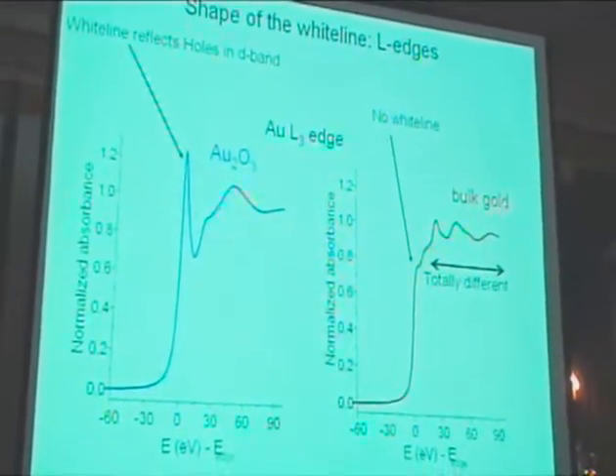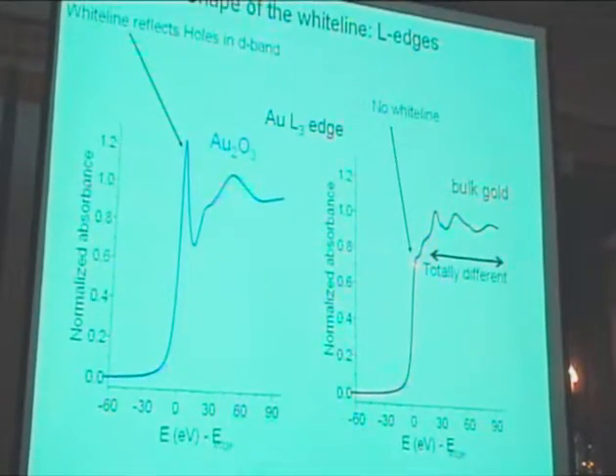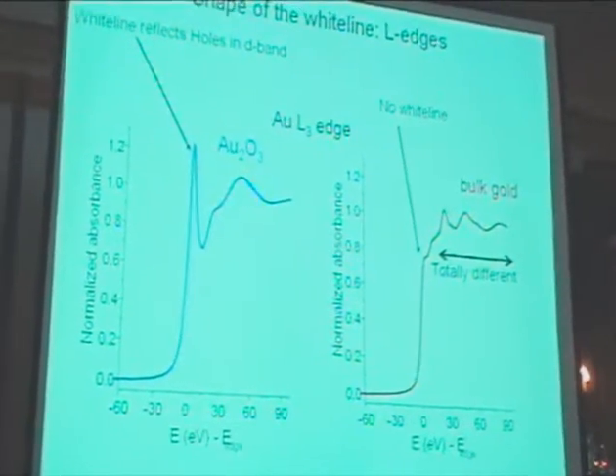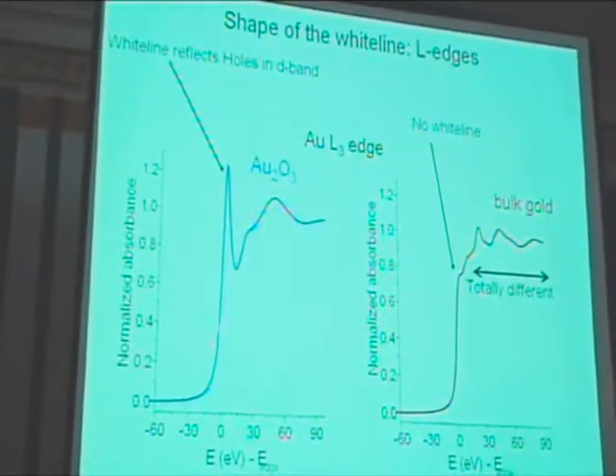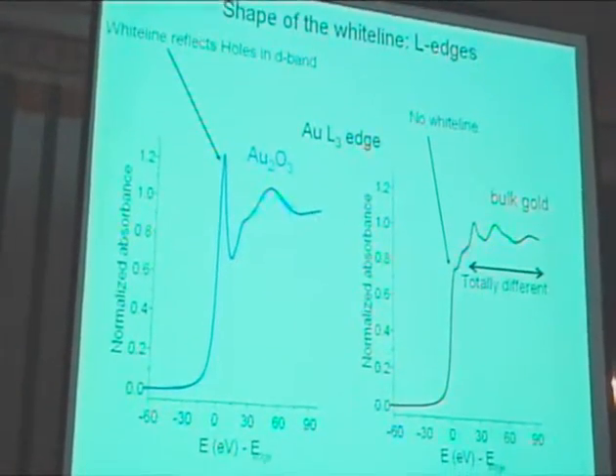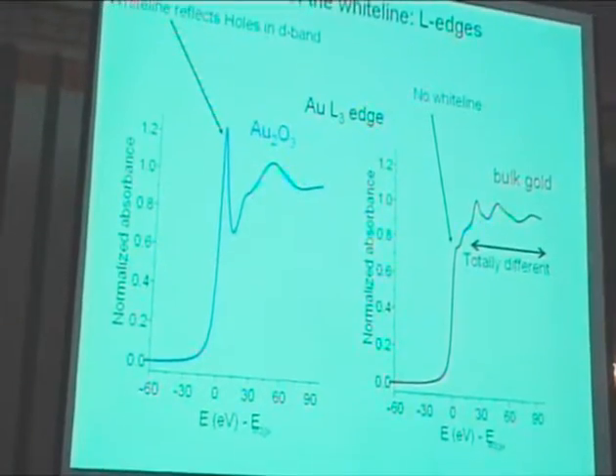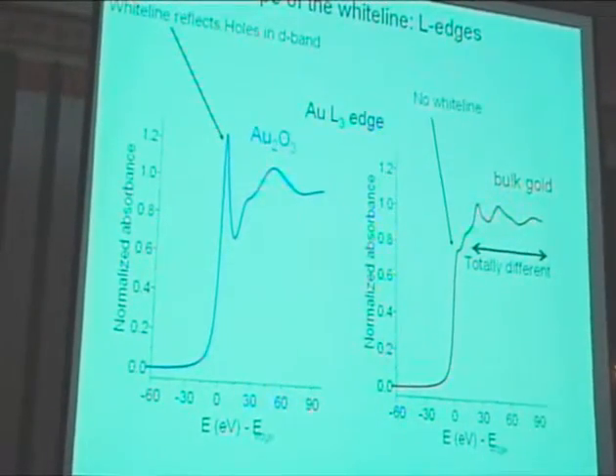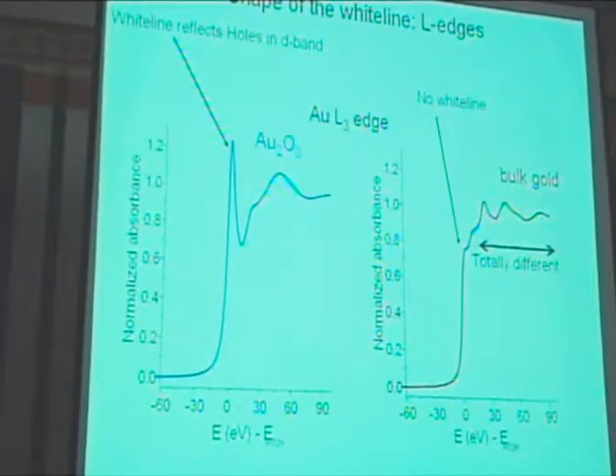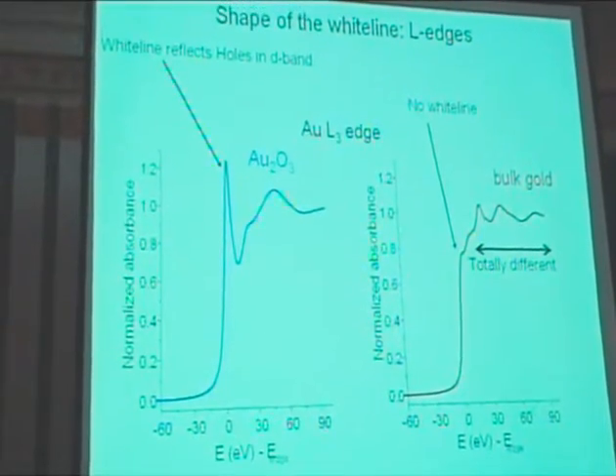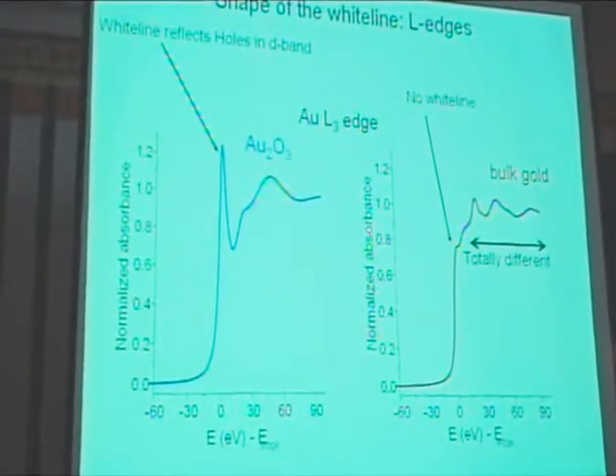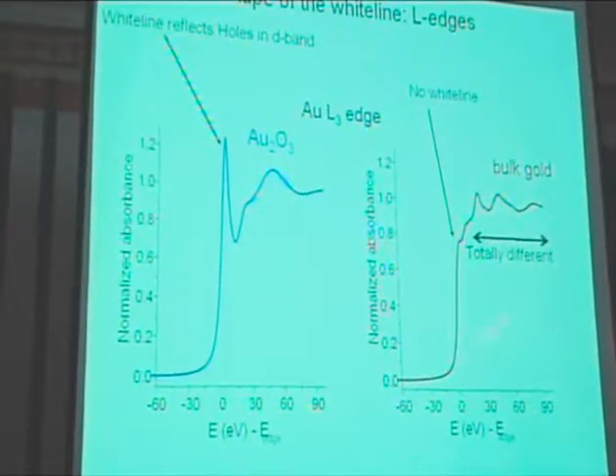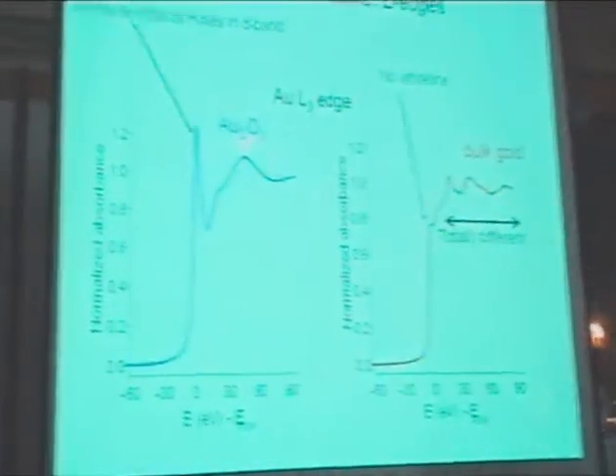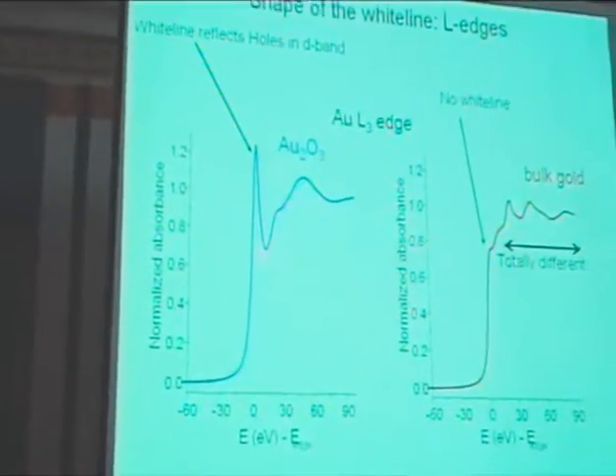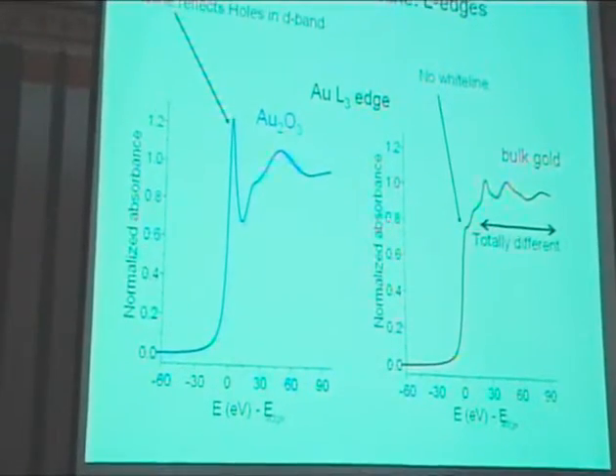And why is it there? If you have metallic gold, it has no white line. If you have an oxidic gold, it has it. And that's because what you do here, the 2p electron is promoted to the 5d level. And that's an allowed transition, p to d. But that means there must be holes, there must be an empty place for the electron to go to the 5d level. Now in gold, the 5d band is full, whereas in the oxidic gold, the 3+, you have empty holes. So now the electron can go here, so you see intensity. That's the story.